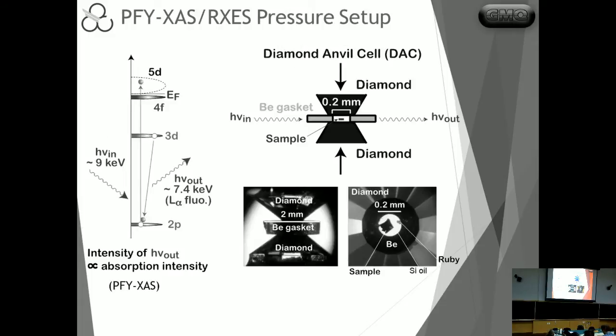So from the simple absorption spectra, they changed to a technique called the partial fluorescence yield X-ray absorption, and the X-ray emission spectra, to help clarify the behavior of the valencies here. So the idea is that instead of just looking at what energies provoke an absorption of the radiation, you start looking at the emission.